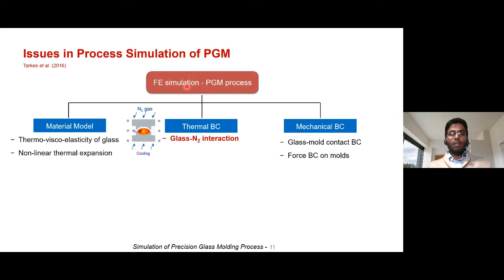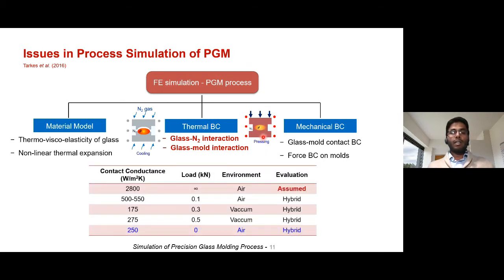And then there is the second thermal boundary condition, which is the glass mold interaction. During the pressing operation, there is glass mold heat transfer happening, and also during the cooling stage, due to which the glass is able to cool down. In literature, again, there are several values being used, and hybrid experiments were done, hybrid in the sense of coupled experiment as well as numerical simulation. Based on these experiments, they were able to find some values. For air conditions, when there is no load acting on the molds, the heat transfer coefficient was found to be 250, which was useful for our simulations, which I'm going to explain in the next slides.